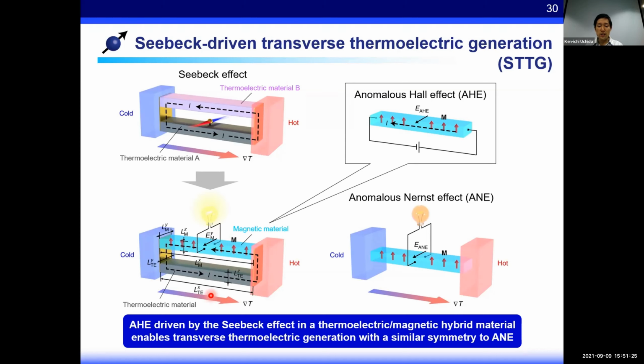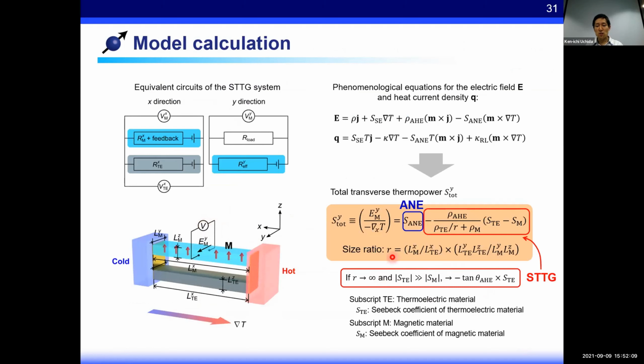But what is important here is the size ratio between magnetic and thermoelectric materials. For example, please imagine the situation where the thermoelectric layer is very thin and highly resistive, and the magnetic material is very large. In this case, even when the thermoelectric material exhibits the Seebeck effect, the charge current generated in the magnetic material is very small. Charge current density becomes very small. In contrast, if the thermoelectric material is very large and the magnetic material is a thin film, a large charge current density can be obtained in this configuration. So this is summarized in the size ratio. In addition to the transport properties, we can optimize the relative dimensions of each component.